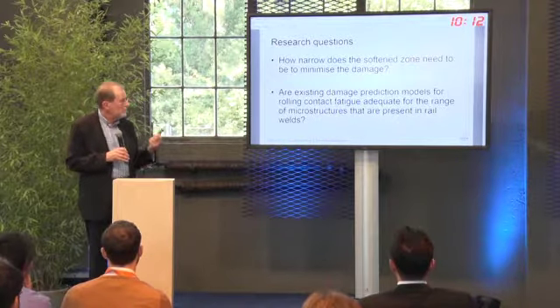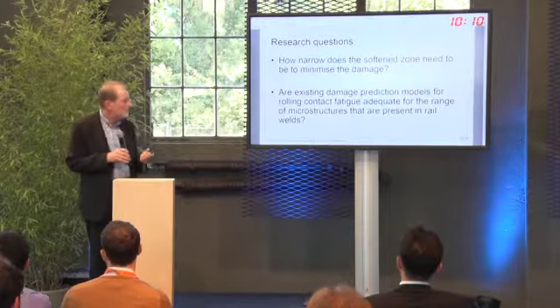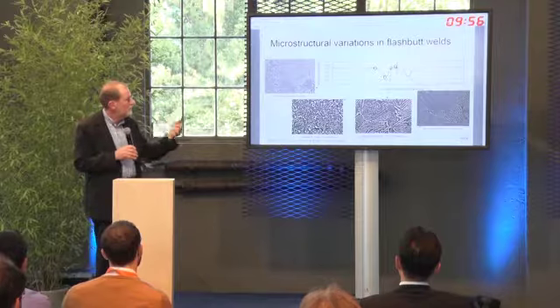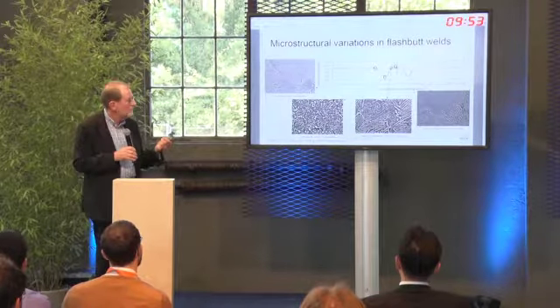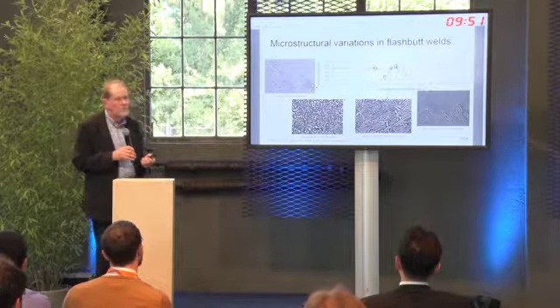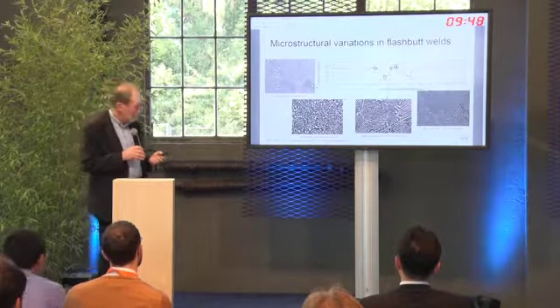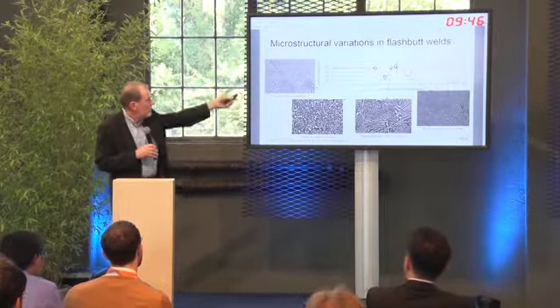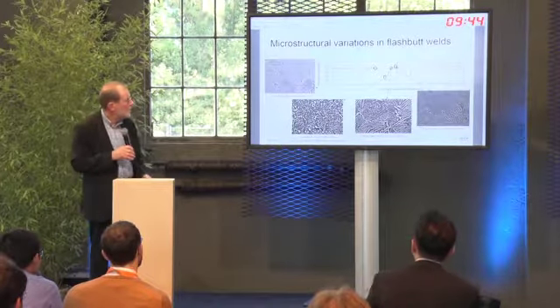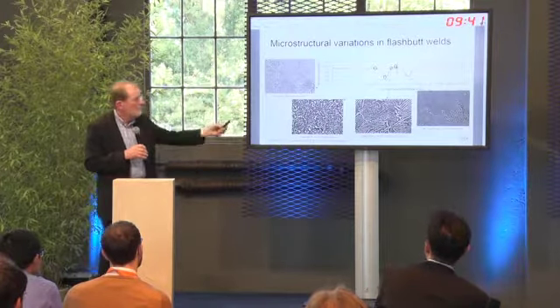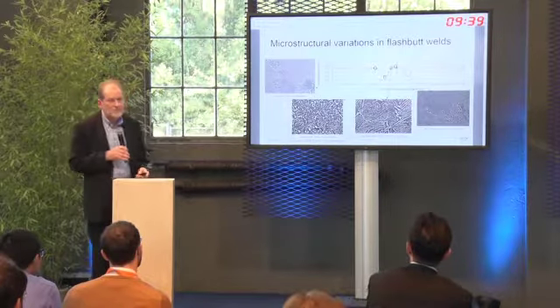I guess the question that's probably more relevant to this audience is really, are our damage prediction models for rolling contact fatigue adequate for the stuff they've got in welds? Because welds do have quite a range of microstructures. So this is illustrated here. This is a hardness distribution along a flashbutt weld in a 1% carbon hypereutectoid rail. So over here on the side is the pearlite in the parent rail. Over on the far right is what you've got in the centre of the weld, or